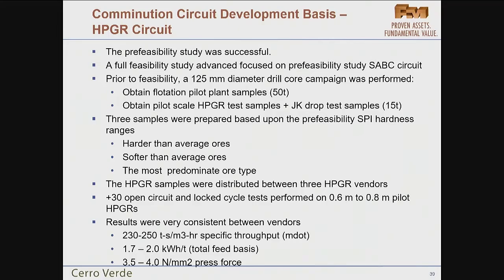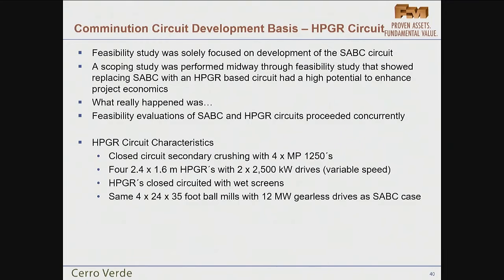We advanced to feasibility. Again, the focus was completely on SAG mills or SABC, but prior to the start of the feasibility, there was more drilling, large diameter drilling, got a pilot plant sample, and got some samples for JK drop tests, and almost as an afterthought, we collected some samples for HPGR testing. Three samples: harder than average, softer than average, and the most predominant. They were divided up to work with three vendors in Germany, multiple tests, very consistent results.